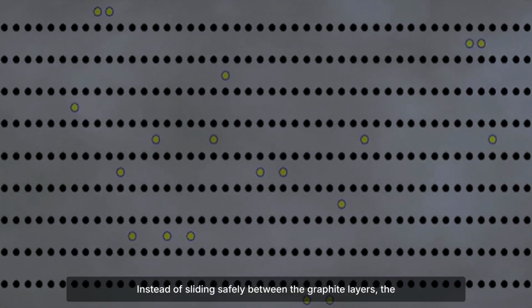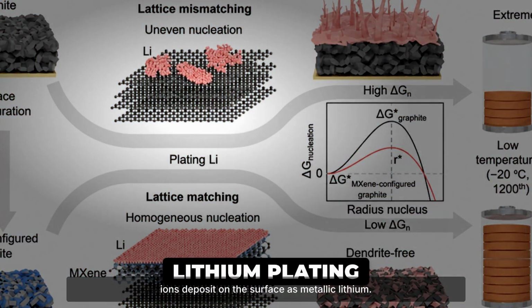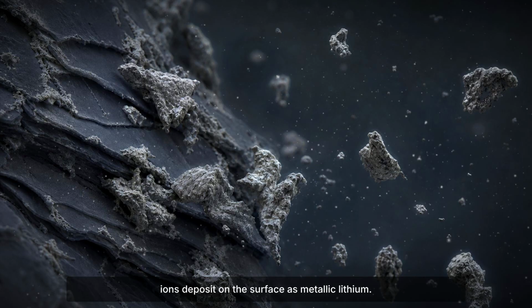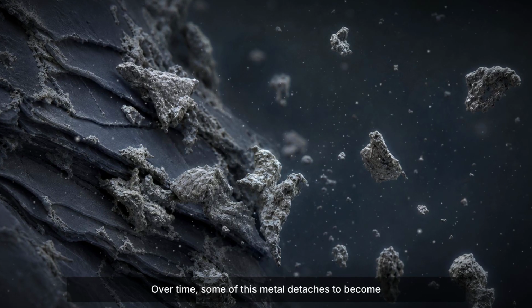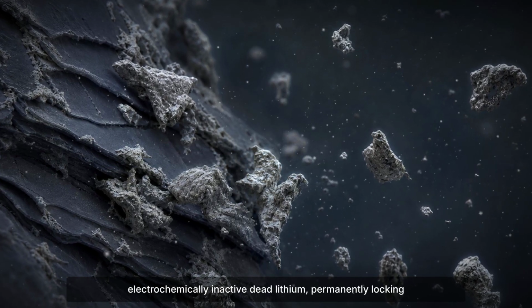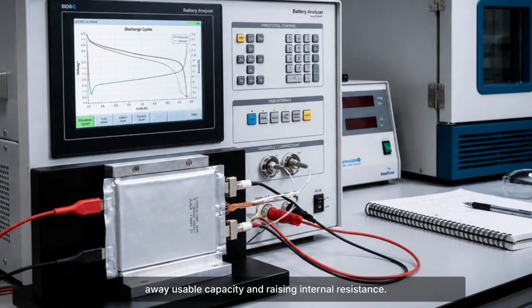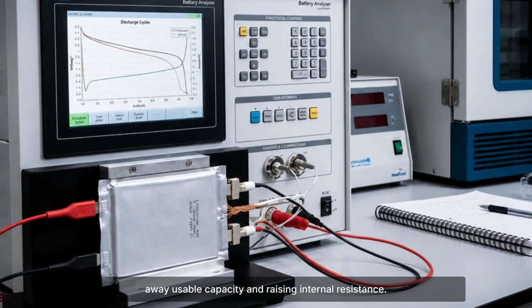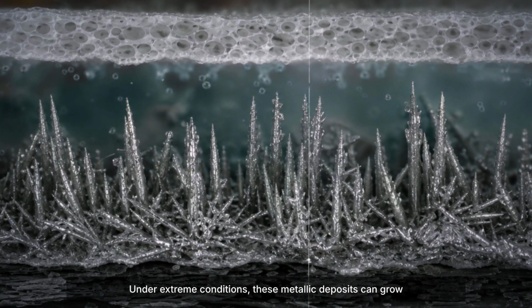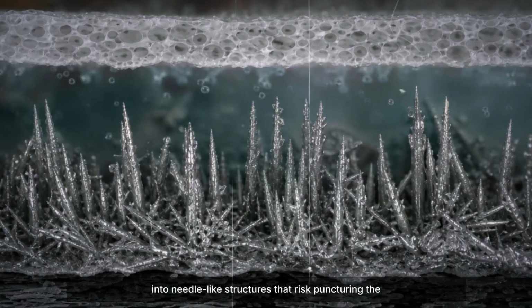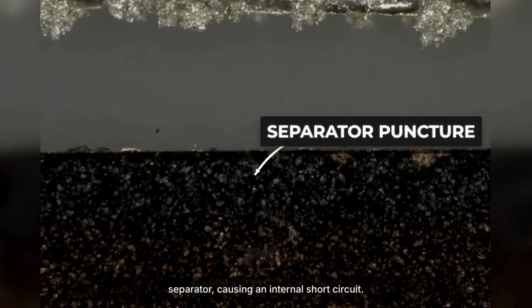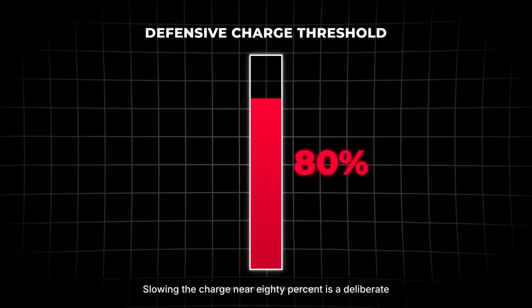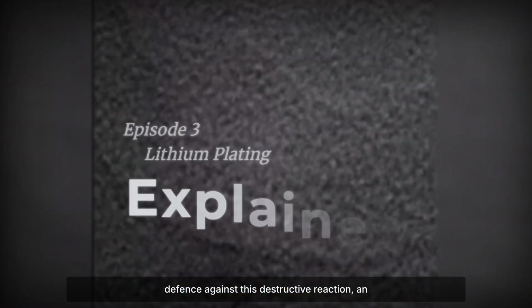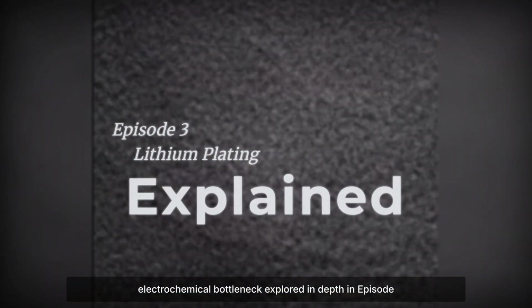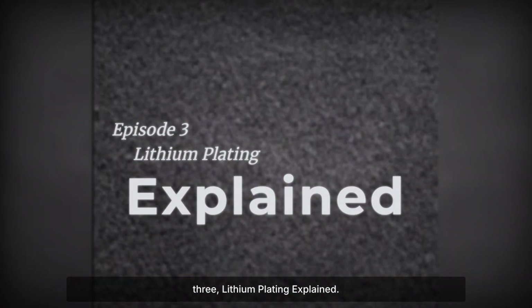Instead of sliding safely between the graphite layers, the ions deposit on the surface as metallic lithium. Over time, some of this metal detaches to become electrochemically inactive dead lithium, permanently locking away usable capacity and raising internal resistance. Under extreme conditions, these metallic deposits can grow into needle-like structures that risk puncturing the separator, causing an internal short circuit. Slowing the charge near 80% is a deliberate defense against this destructive reaction, an electrochemical bottleneck explored in depth in Episode 3, Lithium Plating Explained.